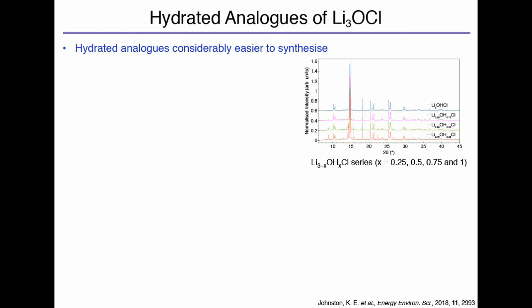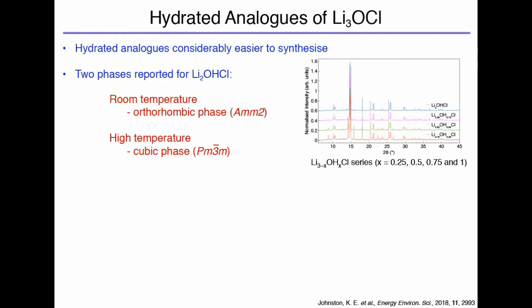So because we'd had no luck with this whatsoever, we decided to change direction slightly. And we decided to look at the hydrated analogues of these materials, which were well reported within the literature. And it turns out you can make them with relative ease. These things literally do just fall out when you heat them, doing exactly the same as we did for the previous material. And when you look into the literature a little bit more, you find that there's actually two phases of Li2OHCl, which is like the end member of the series, if you like. You have a room temperature phase, which is believed to be orthorhombic, and a high temperature phase, which is believed to be cubic.